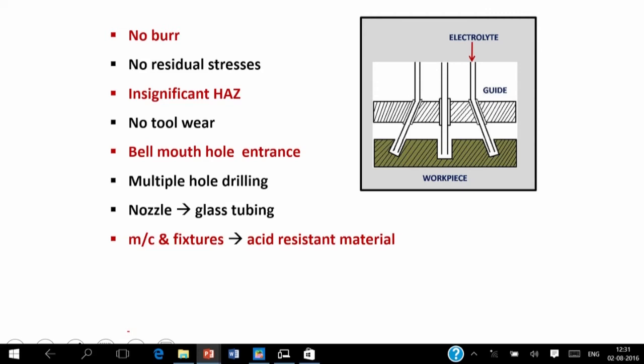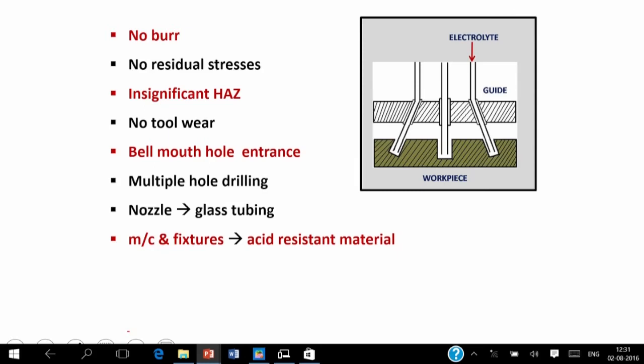In electrostream drilling, no burrs are generated, no residual stress is generated, and temperature is maintained up to 100 degrees centigrade. So that's why there is insignificant heat affected zone. There is no tool wear, bell mouth hole is generated, multiple hole drilling is possible. The nozzle is made of glass tubing, and acid resistant materials are used for the machine and fixtures.